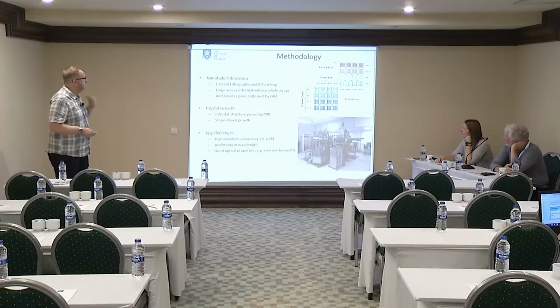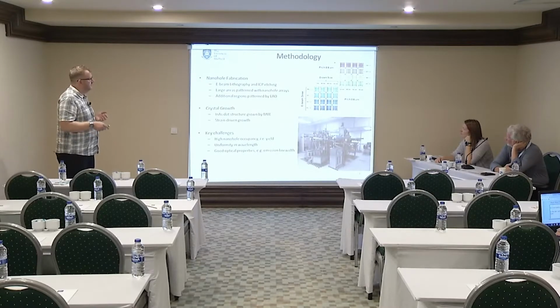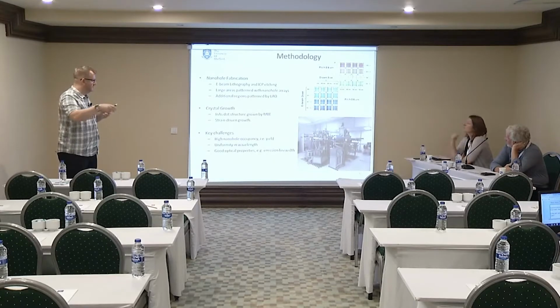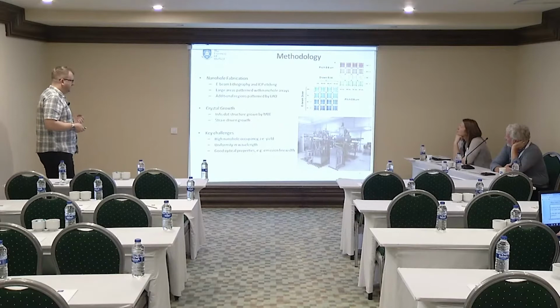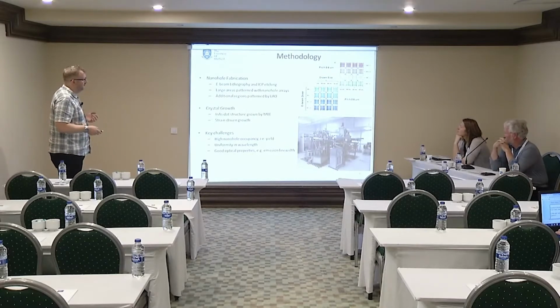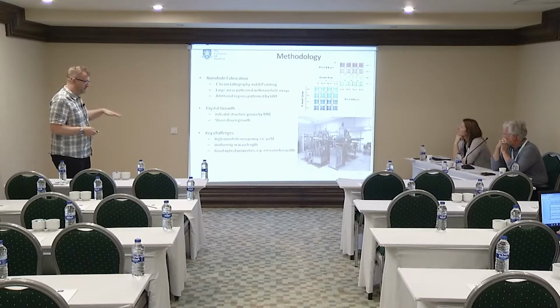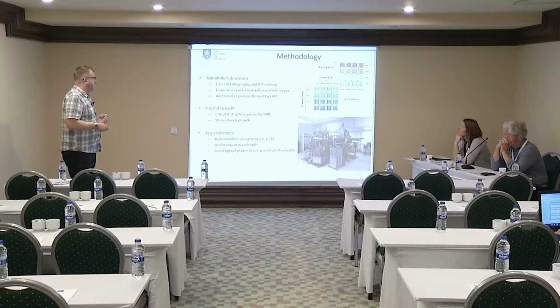So the general approach then is going to be, we have an E-beam pattern which consists of arrays where we have a series of different doses we're also trying to optimize, a series of different sizes of nanohole that we're going to try and make, and also a series of different spacings of those nanoholes in order to look at the competition between formation and migration across the surface. At the same time, what Charlotte did was also pattern some other regions on the wafer using LAO so that we could do the growth at the same time. And then we're going to grow our structure by MBE.